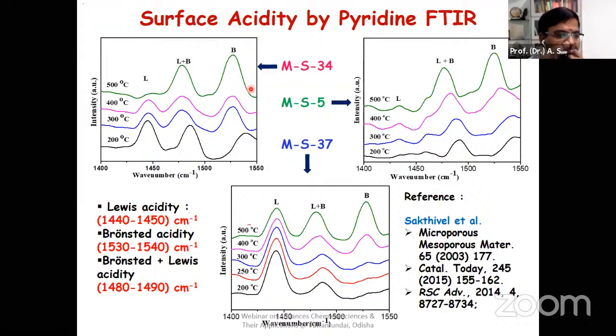Just as in an acid-base titration, where we titrate sulfuric acid versus sodium hydroxide, this is a kind of titration at different temperatures. When you do that, if Lewis and Bronsted acid sites are present, then we can see that the FTIR spectra will show peaks around 1440 and 1540.